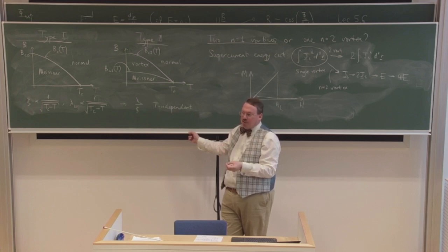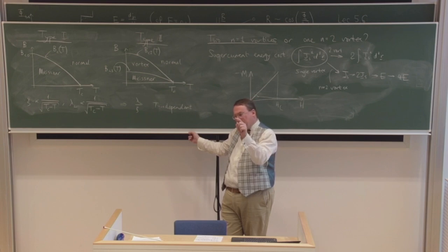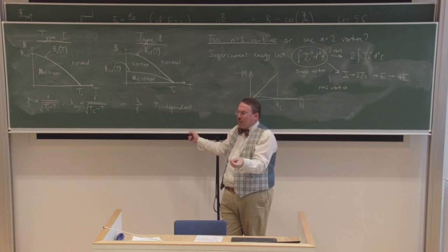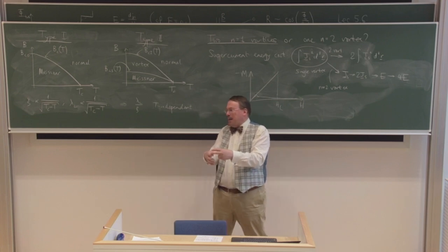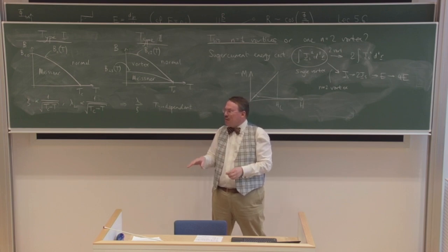Something similar is often the case in superconducting samples. When you go into the vortex phase, there's defects and edges are more likely to be able to nucleate vortices, because there the superconducting order parameter will be suppressed anyway. So it's easier to bring it down to zero and pop one of these things out. So there are nice videos, actually. The nice thing is these vortices are quite big. So if they move slowly, you can actually do microscopy on the surface and see them moving around.